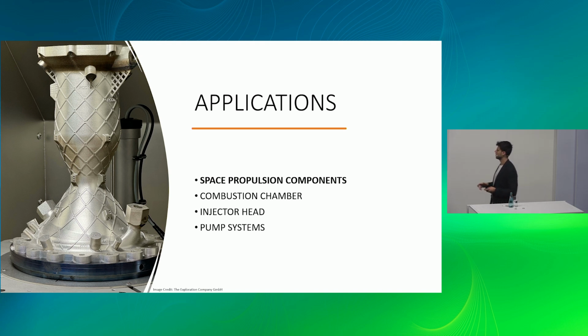And here you can actually see this regenerative cooling cycle. So the fuel goes in here, will go into the manifold, collect and be pumped through very small cooling channels through the part to then be injected from the top side and ignited. The wall thickness of this part is only 4 millimeters, and we have to fit roughly 100 cooling channels inside this entity, which is quite a challenge. So we're really at the edge of the technology here.